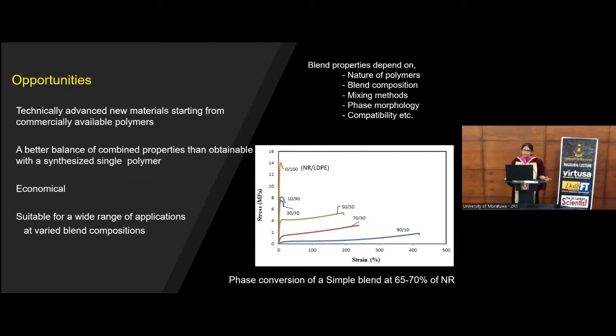This image shows the stress-strain curves of the materials developed using natural rubber and low density polyethylene. Low density polyethylene has high strength but less flexibility, and rubber has high flexibility with low strength. By combining those two materials, different materials can be produced and applied to make high performance products, or products with less performance, depending on the requirement. Normally, in a simple blend, the phase inversion takes place at 65 to 70% of natural rubber.